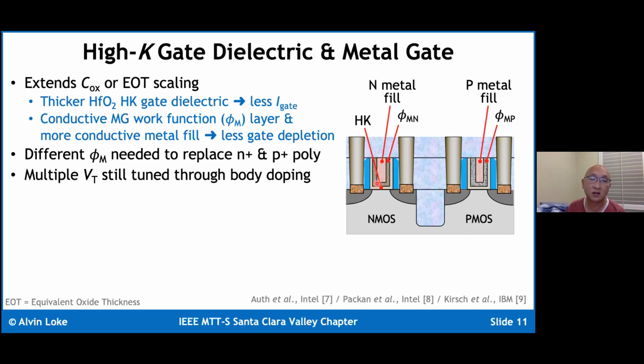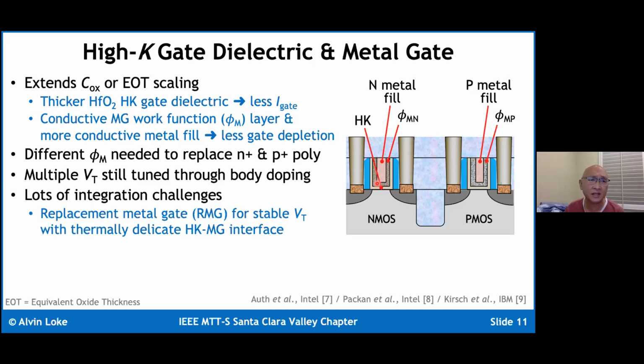Okay, because we're trying to go after a material with a work function that lines up with the conduction band edge in the silicon band structure for N+ poly, and conversely lining up to the valence band edge for P+ poly. When HighK metal gate was first introduced at 45 nanometers, the different VT flavors for a given polarity were being tuned using body doping or implants. HighK metal gate technology is a headache to integrate. There are lots of integration challenges you have to deal with.